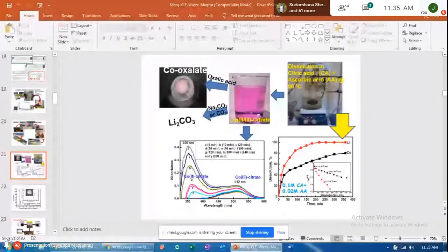Taking mild organic acids, I take a mixture of, for example, citric acid and ascorbic acid. Ascorbic acid acts as a reducing agent, and the citric acid acts as a chelating agent. As I said, cobalt 3+ becomes cobalt 2+, and it gets ejected from the lattice. As soon as it comes into the solution, citric acid will make a complex with that lithium, along with the cobalt. So cobalt and lithium come out from the lattice, and both are stabilized, but that stability constant, the log K value, is very, very small. That means it's a very mild chelating agent or a weak complexing agent.